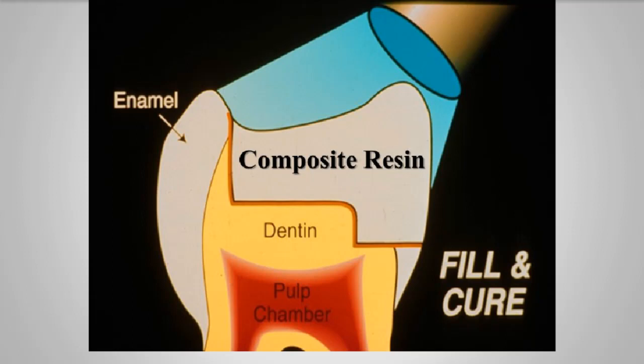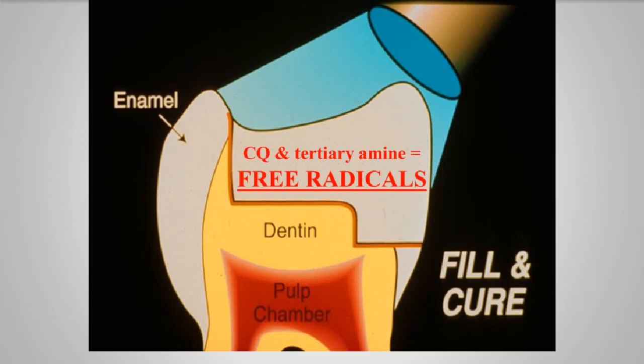That is, to polymerize. Well, in the case of light-cured composites, we do this by infusing this mixture with highly energetic light photons. And that's just a really fancy way of saying we zap it with our bonding lights. And when we zap it with our bonding lights, energy in the form of photons enters into the body of the composite, and these photons interact with a light-sensitive molecule, usually, but not always, a photoinitiator called camphorquinone. And this camphorquinone then in turn interacts with a tertiary amine of some type to generate something called free radicals.